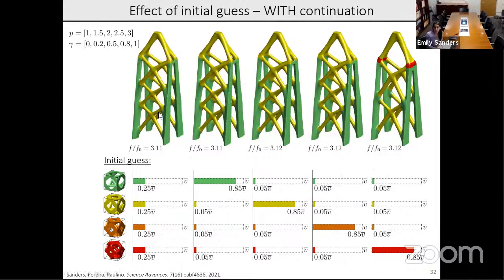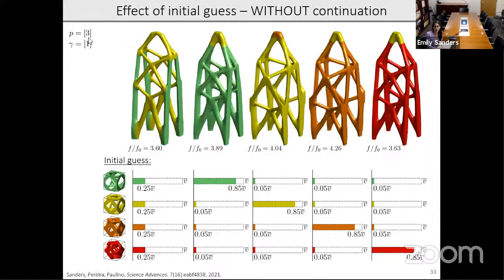And you can see that with the continuation scheme, we basically get the same solution no matter what the initial guess is. This one is a little bit different, but the objective function doesn't change. Now, if you do it without continuation, here we set P equal to 3, gamma equal to 1 for the whole optimization process. Now you can see that whichever material dominates in the initial guess is going to dominate in the final solution. When you have a uniform initial guess, it looks a lot like what we had on the previous slide, but the objective function is much higher.